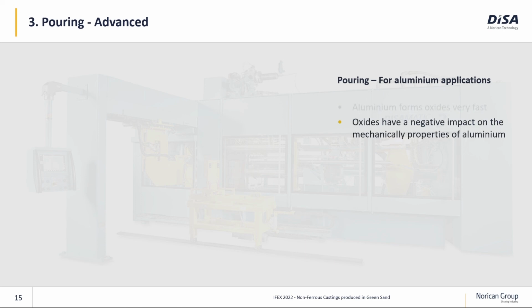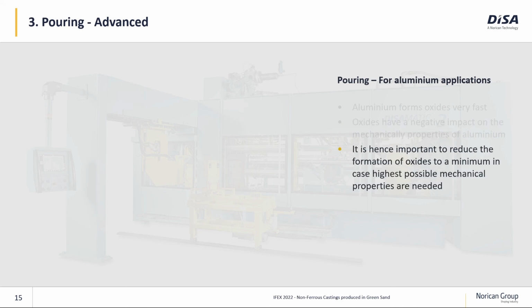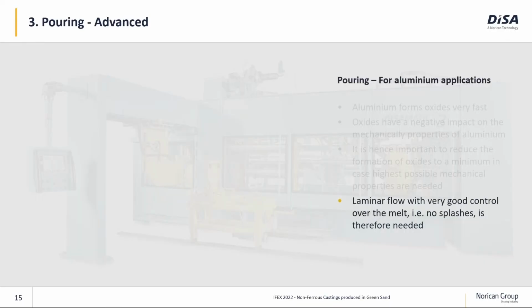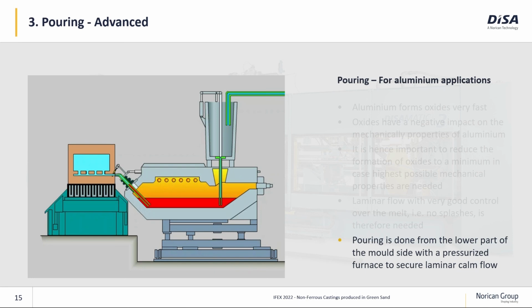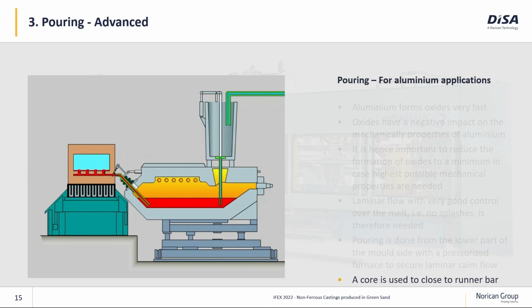Aluminum forms oxides very fast, and these oxides will reduce the mechanical properties. And in case we are producing aluminum castings where we need to obtain the highest possible mechanical properties, it is super important to reduce the formation of oxides to an absolute minimum. This means we need to have a laminar flow, and we need to avoid splashes of the metal, etc. We obtain this by using low pressure pouring, where we fill the metal through the side of the mold and slowly fill the metal into the mold. To get high productivity, we have a small core closing the runner bar, meaning we can move away from the mold with the pouring device before the metal is solidified.